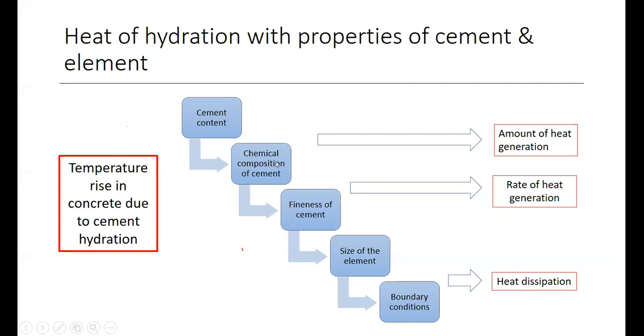And if the chemical composition has more C3S or C3A, with higher fineness. Higher fineness means the particle size of the cement is very low. It means it has more surface area, which is very good for the reaction. It generates heat very rapidly. So it is basically dealing with the rate of heat generation. And then the size of the element: big sizes generate more heat.